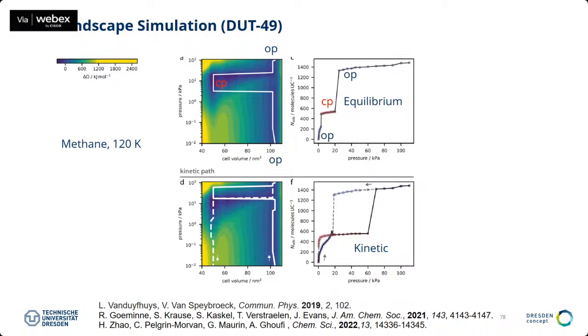That's also why we live, probably. If we would be in thermal equilibrium, then we would probably be dead. And so life is more exciting and interesting if there are barriers. And there are a lot of energetic barriers. If you want to swim in the deepest ocean, you realize you have to go over a mountain here to come to the closed pore, to the contracted pore phase. And this is basically the reason that this structure is overloading itself. It's swallowing more methane than it can take up before it's contracting to the contracted pore phase, and then it's opening up again here. So these strange phenomena are purely kinetic phenomena, but this does not mean that you can wait longer and then you don't observe it.